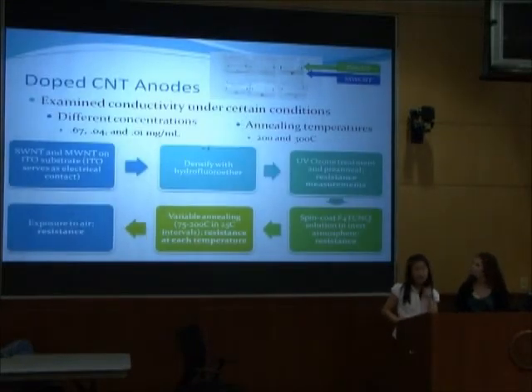Our process for making the carbon nanotube anodes was basically, first we put the single-walled and the multi-walled nanotubes on the ITO substrate, where the ITO served as the electrical contact. Then we densified them. After that, we pre-treated the carbon nanotubes. Some of them we placed under a UV ozone treatment, and some of them we pre-annealed at different temperatures.